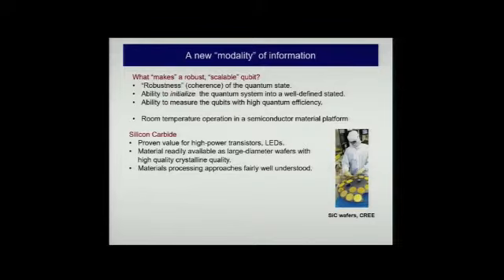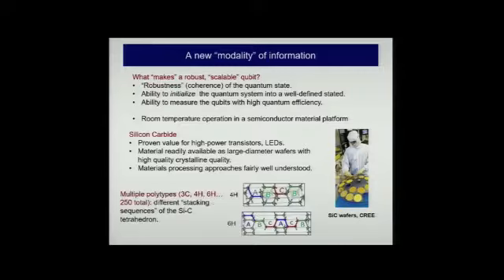Silicon carbide, as you can see here, from this researcher who's working at Cree, a company that's actually been developing silicon carbide and other what are called large band gap semiconductors for quite a while. This is a material in which you can get 6-inch wafers. It's a material that's proven its worth already in more traditional information technologies, for high power transistors, for LEDs. It's readily available as large diameter wafers. The crystalline quality is good. And because it has been already in device production, the approaches to taking that material and shaping it into a device are generally, I would say, fairly well understood, maybe not well understood enough for what we want, but at least we have a starting point.